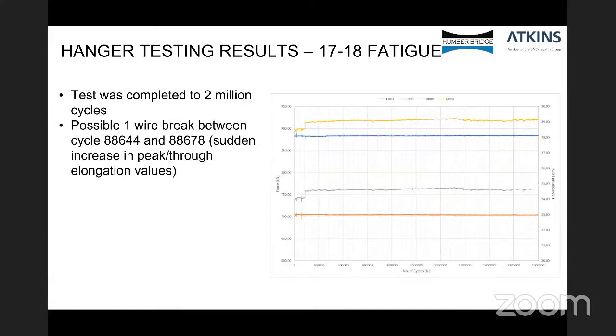So the test was completed to 2 million cycles. There was possibly one wire break between cycle 88,644 and 88,678 because of the sudden increase in the peak through elongation. So you can see that on the graph there with that increase in elongation of the yellow line and the grey line. And that's indicative of fatigue failure during the testing. However, throughout the rest of the test, there was a very steady displacement, proving that there was no other damage during the testing. Look on to the next slide, please.